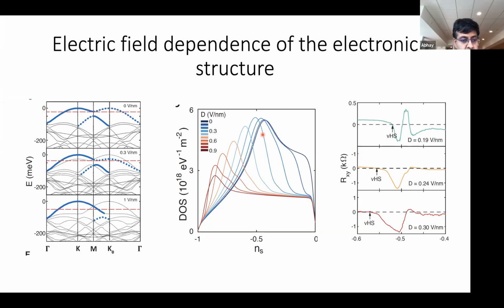That should happen also, but within this calculation, all that's happening is that there's an on-site potential difference. So let me take you through a little bit of detail of this. The dashed line here is the valence band from one layer, and the solid line is the valence band from the other layer. As you start to apply this electric field, the dashed line starts to come down and the solid line starts to go up. That's simply a potential difference between the two valence bands on the two layers. And this is the coupling between the two layers, the bonding and anti-bonding. But the primary effect here is simply the on-site potential difference between these two. So the Rashba for these kinds of electric fields is small.